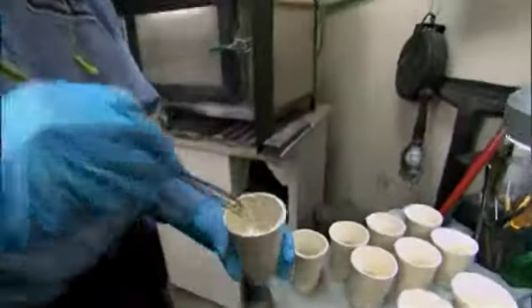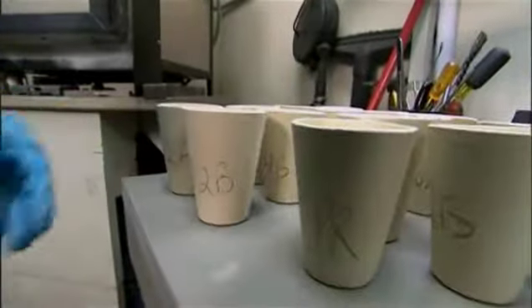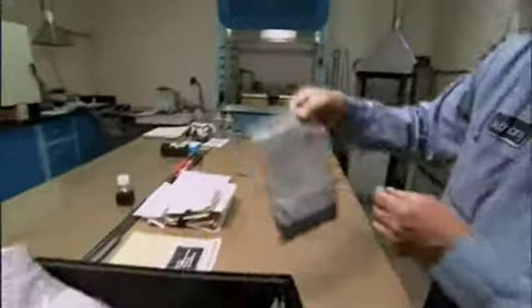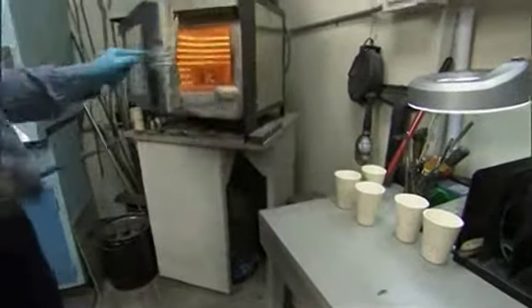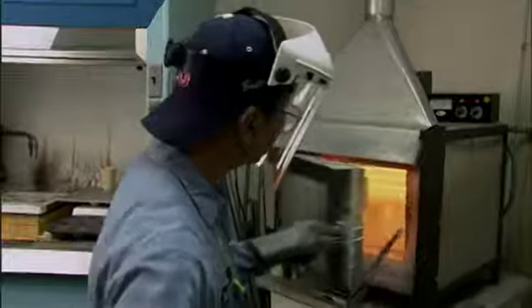Each crucible containing the mix is marked with an assay number that matches the customer's package of powder. After he's weighed these sweeps, he will take the material and put them in a muffle. The muffle is an electric oven, basically. The samples are baked for 45 minutes at 1600 degrees Fahrenheit. What's going on at that time is a miniature smelting operation.